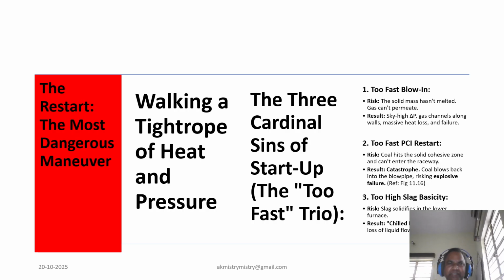Sin number three, too high slag basicity. The risk: the slag solidifies in the lower furnace. The result: a chilled hearth, a complete and total loss of liquid flow to the tap hole. The furnace's circulatory system blocks and the situation becomes dire.